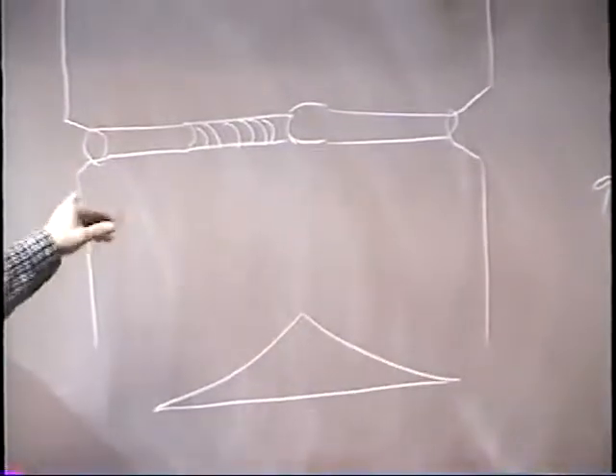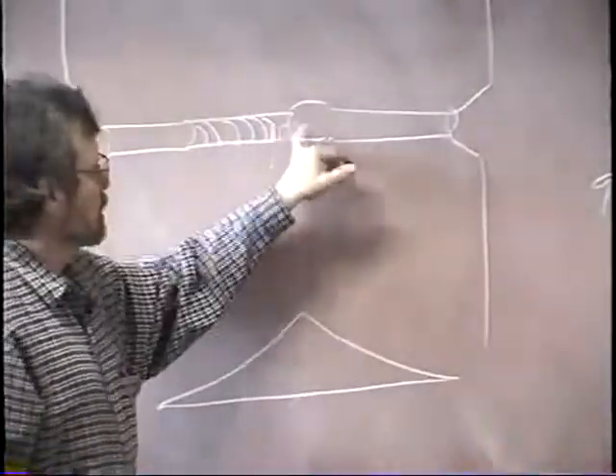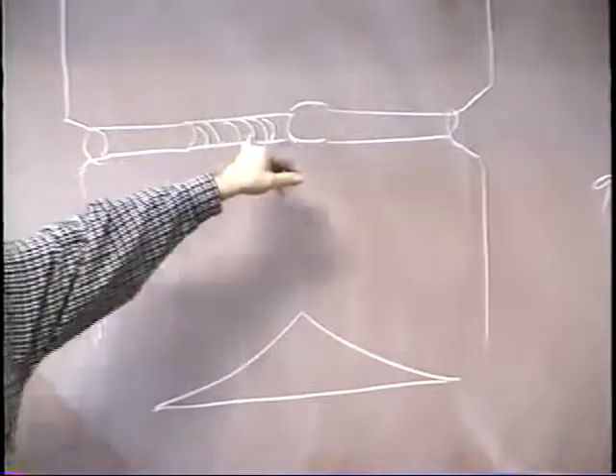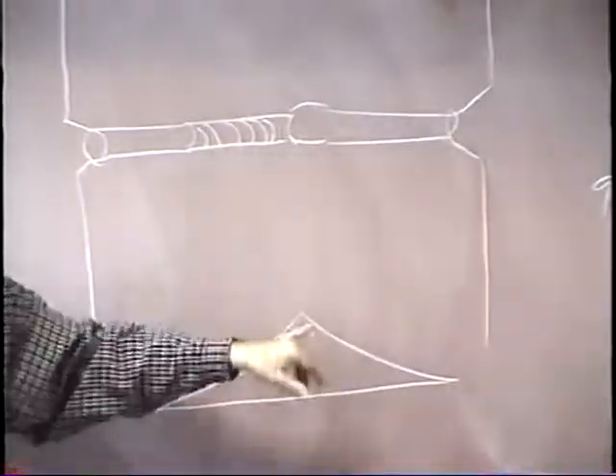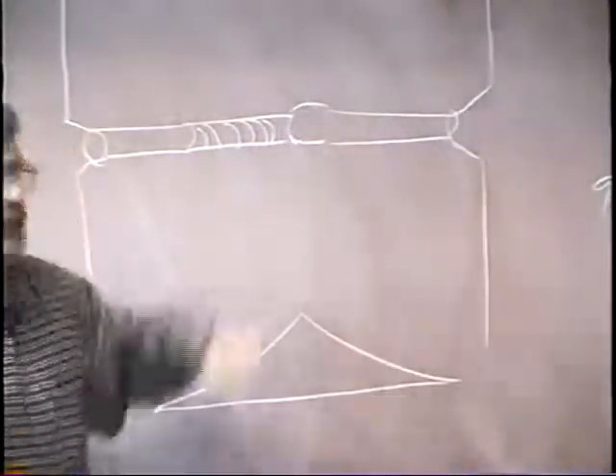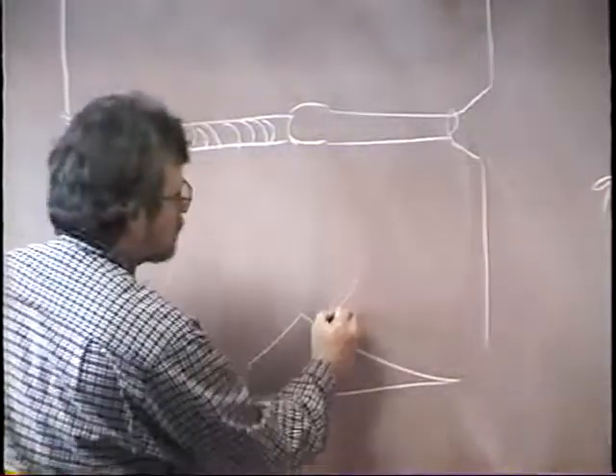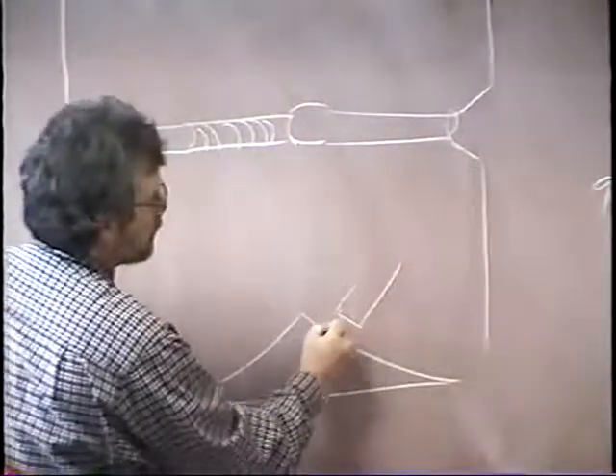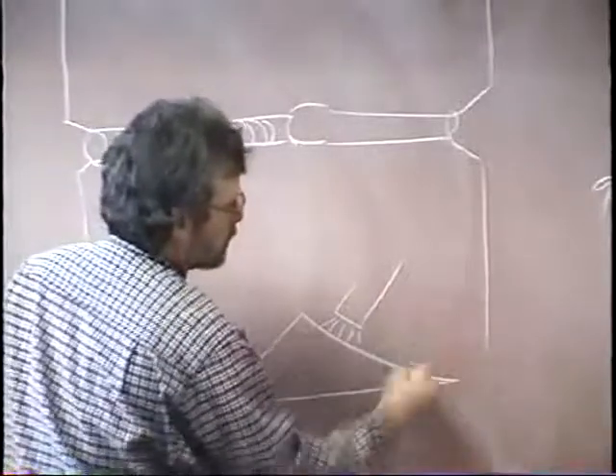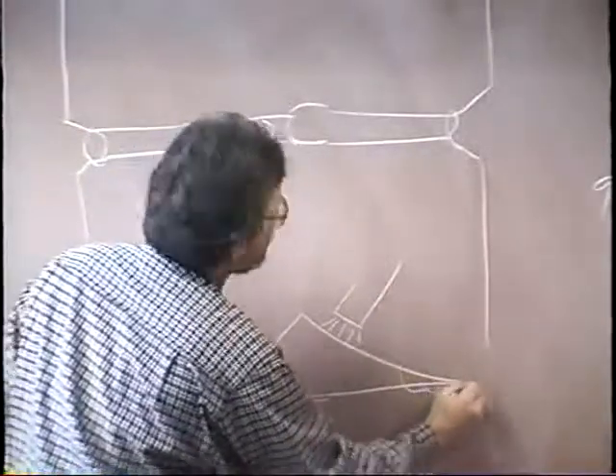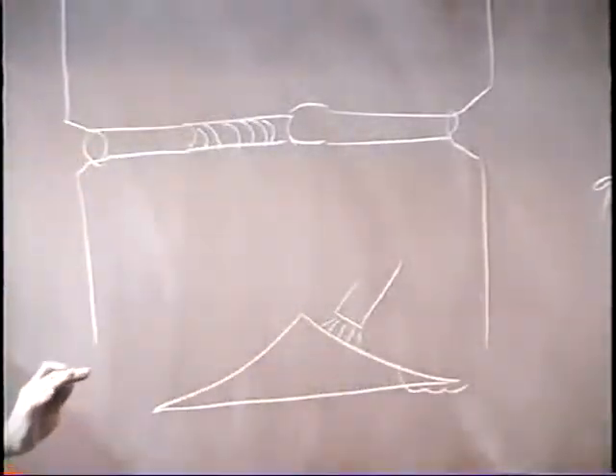Well, the trick is to tie into each tack coming out and going in. Well, coming out, it's not too bad. If you've feathered it properly like this and you've got that big old keyhole, just use the technique of starting up here, come out slowly, and burn through that tack before you reach the end, and it's going to be nice and smooth.